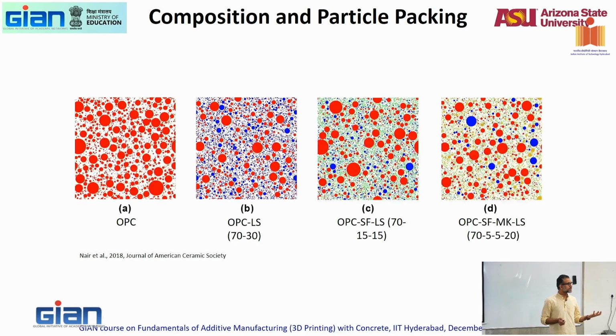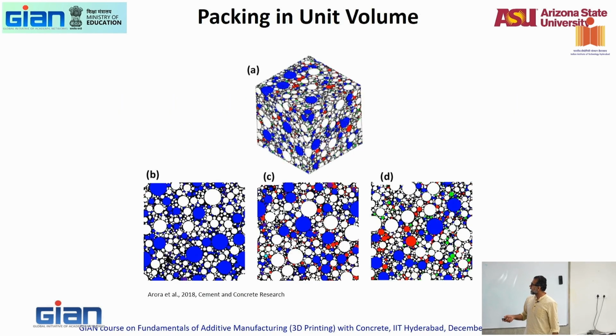Why is it important to reduce the amount of cement in the system? It'll be cheaper, but think about 3D printing. When you're 3D printing a wall with extremely high exposed area and a large amount of cement, what are you going to get? Higher shrinkage cracking, correct? One of the most important problems with 3D printing is shrinkage cracking, which we will see later. So to control shrinkage cracking, your best possible option is to control the amount of cement, which means you have to fill it with some other particles, maintaining your extrudability and buildability at the same level. And here is what's packing in a unit volume in 3 dimensions. You will see all of this in the evening, I hope.